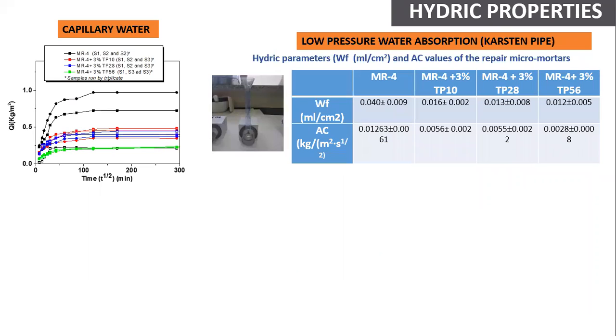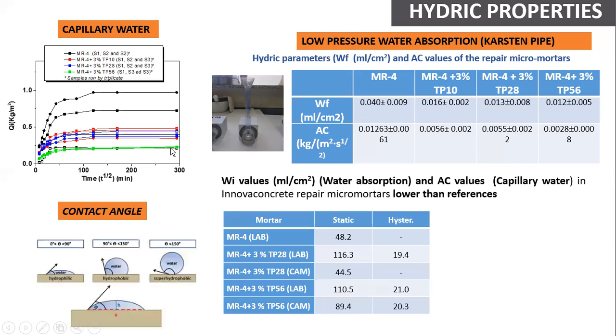And with respect to the hydric properties, we have to point out that the incorporation of these UKTP products reduces the water absorption and the capillary water. The highest proportion of polydimethylsiloxane in the product, the better hydrophobic performance. Finally, with respect to the contact angle, here in this table I show you some of the results.